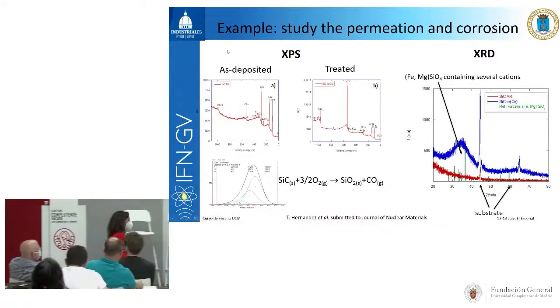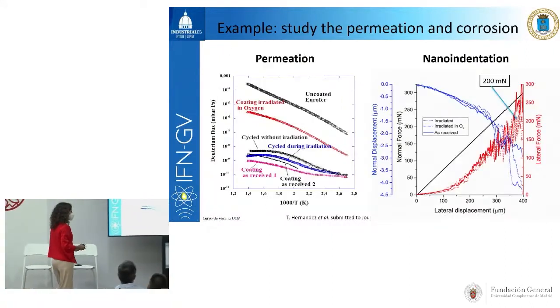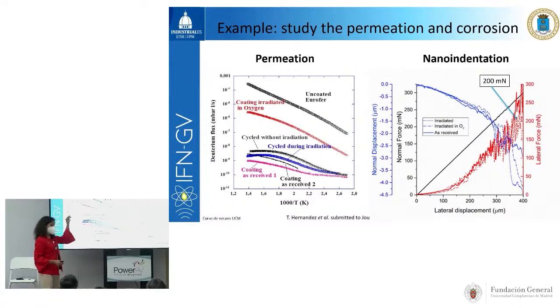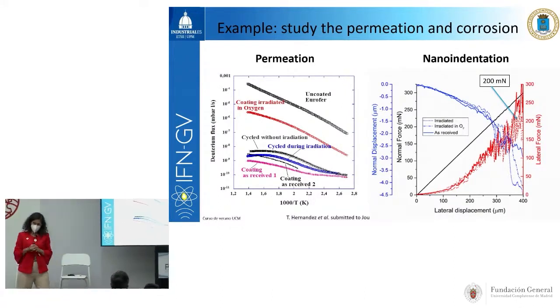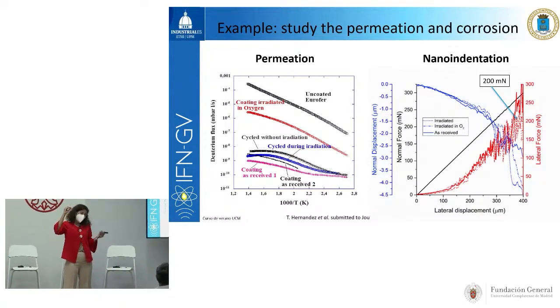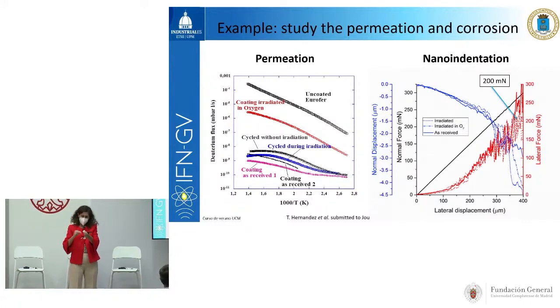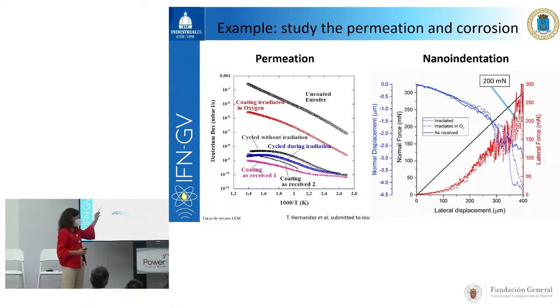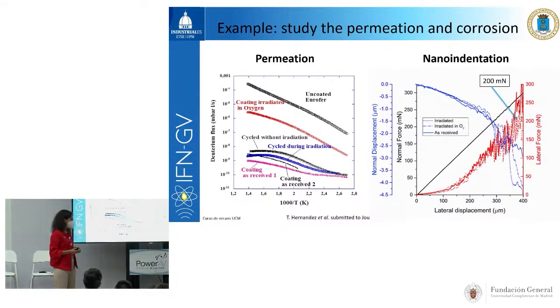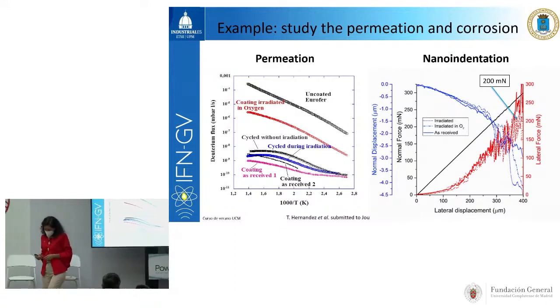And there is also another very important thing which needs to be considered. Basically here we were measuring the permeation reduction factor. So we were measuring, if tritium, in this particular case we were using hydrogen, to see if the hydrogen can penetrate through the barrier, if we have created some defects in the barrier. And what we did was measure the permeation before and after the irradiation, and we observed that there is no change.